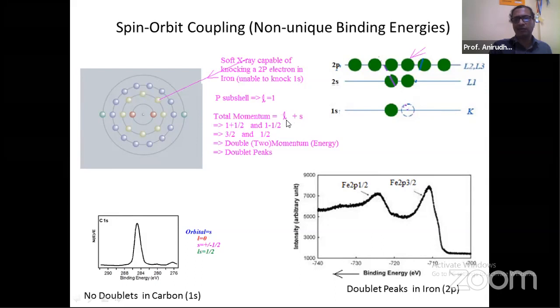Now, if L is a value which is different from 0, like what we find here, where L is equal to 1, then S is the spin quantum number, which can be either plus half or minus half. So if L is equal to 1, we would get the total momentum to be equal to 1 plus half and also 1 minus half, because S will have two values, plus half and minus half. So the total momentum is not unique. There are two different values for the total momentum. Either it can be 1 plus half or 1 minus half, or in other words, either 3 by 2 or 1 by 2, which means there are two momentums, or in other words, two energies associated with them.